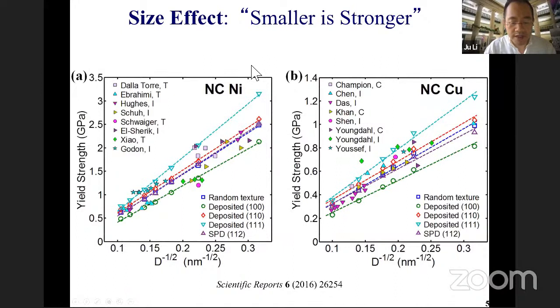However, with nanomaterials, there is something called a size effect, which is smaller is stronger. What you see here are bulk nanocrystalline nickel, their room temperature flow strength as a function of the inverse of their grain size. And in something very soft like pure copper, without any alloying element, just by reducing the grain size to tens of nanometers, you can have yield strength on the order of a gigapascal.